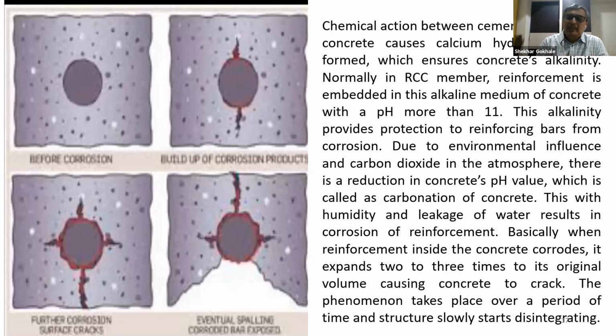Our experience suggests that buildings from 1950 to 1960 and 1960 to 1970 are comparatively better than buildings between 1970 to 1985 because of the cement problem. There was a shortage of cement during that period, and the grade of concrete was M15. In earlier days the concrete grade was also M15, but the workmanship during 1950 to 60 or 1960 to 70 was better compared to structures constructed between 70 and 85. Practically, we observe the buildings between 50 to 70 are better than buildings between 70 and 85. After 85, the grade and quality of concrete started improving.